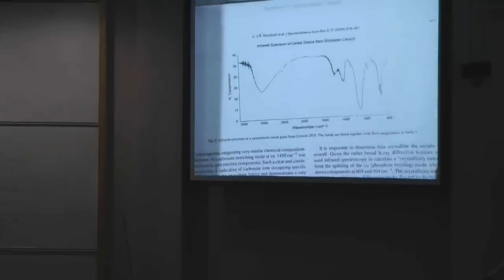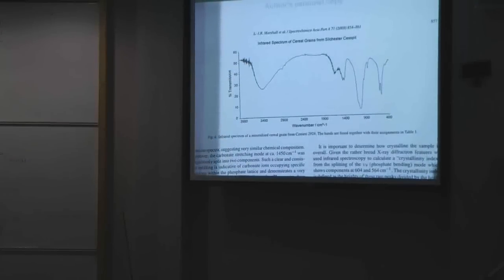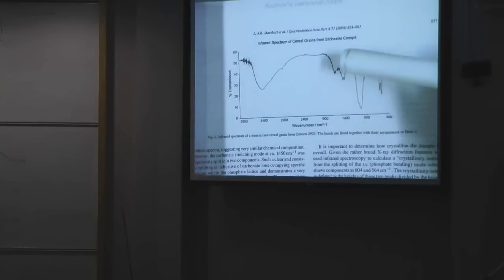Why did these preserve so quickly? It's the perfect combination of having carbonate and phosphate ions present together. Carbonate from the background geology around Silchester, which is chalky, phosphate from the cesspit environment. And when you look at the infrared spectra of these objects, you find spectra that show there's a phosphate peak there, that's this peak around about 1,000 wave numbers, and there's a carbonate peak.